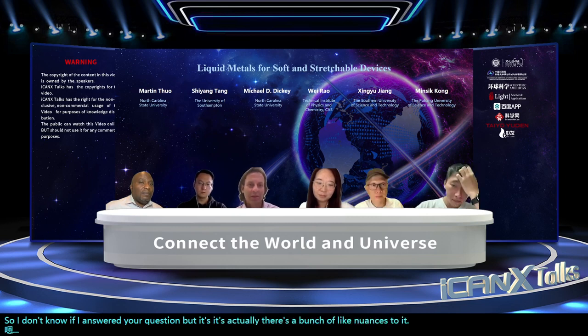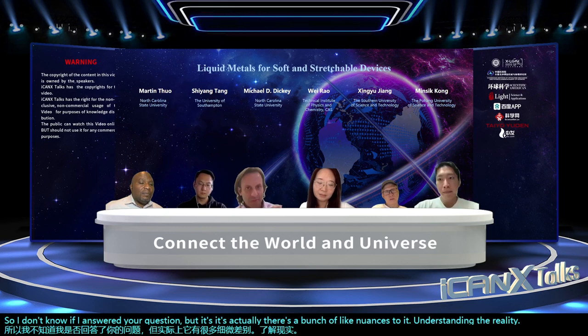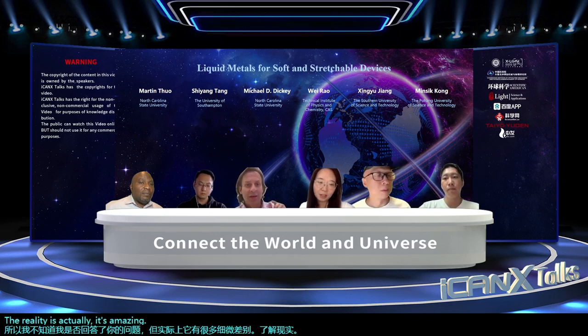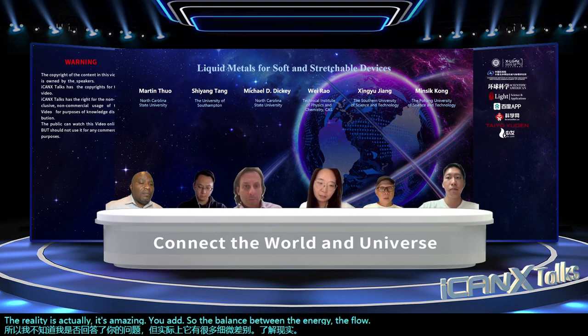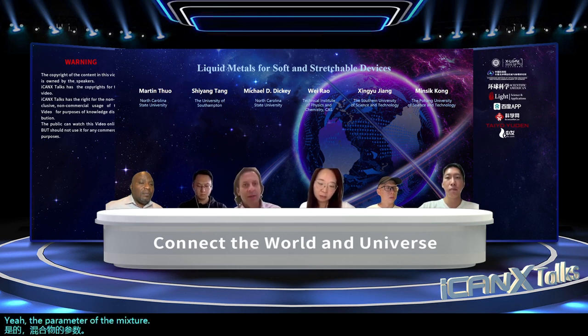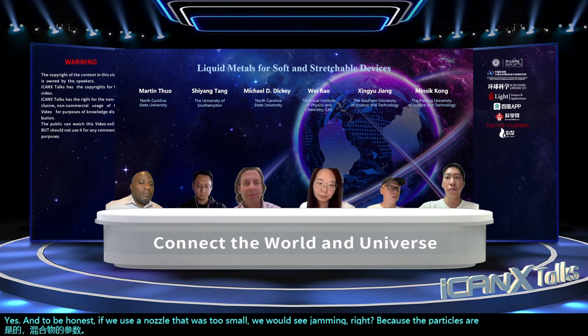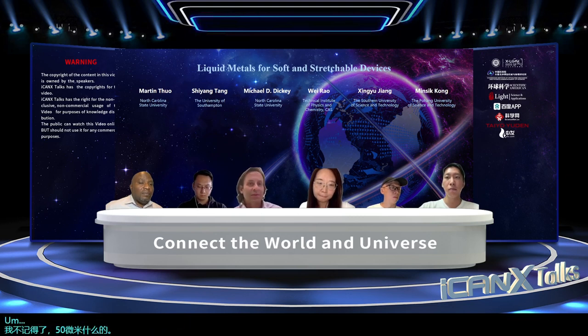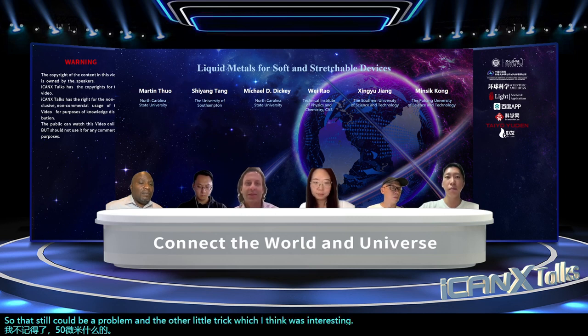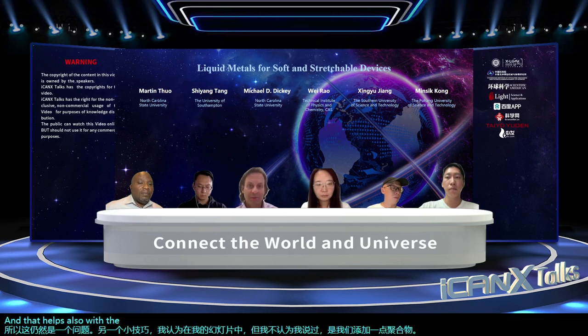Understanding the rheology. The rheology is actually amazing. There should be a balance between the rheology, the flow rate and the parameters of the mixture. Yes. And to be honest, if we use a nozzle that was too small, we would see jamming, right? Because the particles we're using are like, I don't remember, 50 microns or something. So that still could be a problem. And the other little trick, which I think was in my slide, but I don't think I said it, is we add a little bit of polymer. And that helps also with the printing, with the rheology.